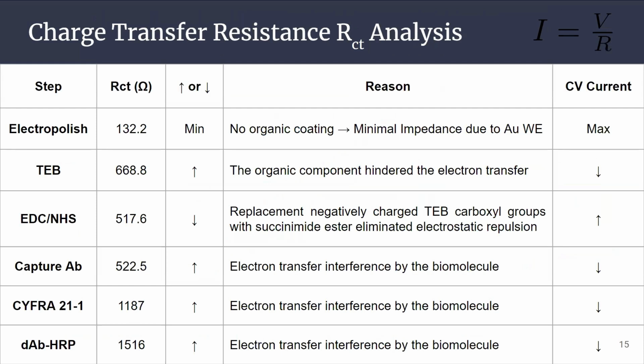We observed a minimal charge transfer resistance after the electrode polish, since there was no organic coating, and it increased after the TEB addition because the organic component hindered the electron transfer. Resistance decreased after the carboxyl group's activation due to partial elimination of the electrostatic repulsion, and after each biomolecule was added, such as the capture antibody, CYFRA, and the detection antibody, the resistance increased because of the electron transfer interference. Conversely, the opposite happens in the CV scans, following Ohm's law.